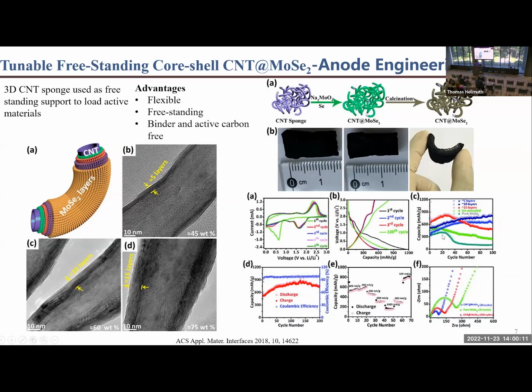And if you see this figure, you can see that when we go to 15 layers, the performance increases, but after 20, 30, or 40 cycles, the performance degrades very quickly. This means that although with active mass increase, we have increased performance, it's not stable. With 10 layers, we got the optimum performance, and it's very stable up to 100 cycles. So it means that active mass has to be optimized, and only then can we get a better performance.